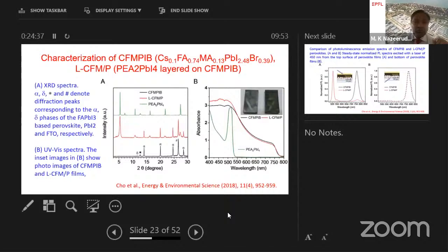That's a 2 theta. And now if you look at the bottom, that's the black line. We have this around 14.9. This is a characteristic peak for the three-dimensional perovskite. In the middle, you do have a two-dimensional perovskite peak and, at the same time, a three-dimensional perovskite peak. Now, this is just XRD data.